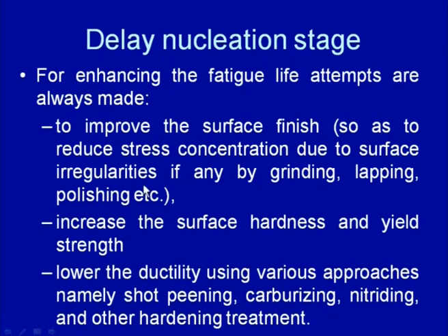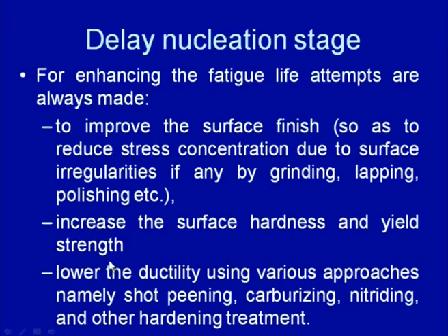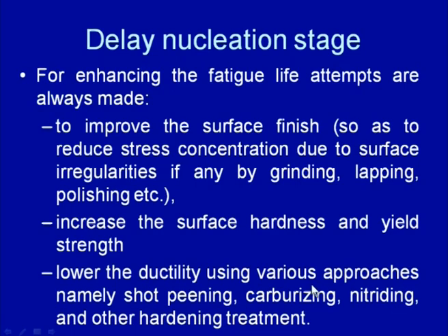concentration due to the surface irregularities, and this can be done by grinding, lapping and polishing the surface of the component, and increasing the surface hardness and yield strength so that the micro level deformation by slip can be reduced, and reducing the ductility using approaches like shot peening, carburizing, nitriding and other treatments. So, the surface hardness and yield strength and reduction in ductility can be achieved through these